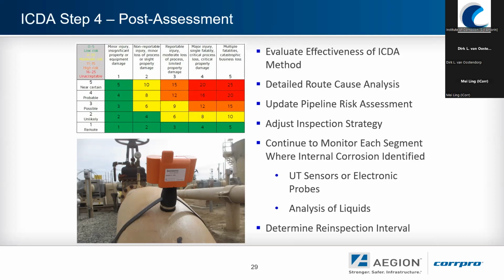And then if there are severe enough locations with corrosion taking place, but not to the point where they mandate repairs, continuous ongoing monitoring may be required. That can consist of online chemical analysis of the liquids flowing through the pipeline to monitor any trends for the corrosive elements. It can also go to installation of permanent UT sensors or electronic probes at specific locations. As seen there on the left, there's a PermaSense UT detector at the top of a 90-degree L, which was found to be a highly corrosive area.